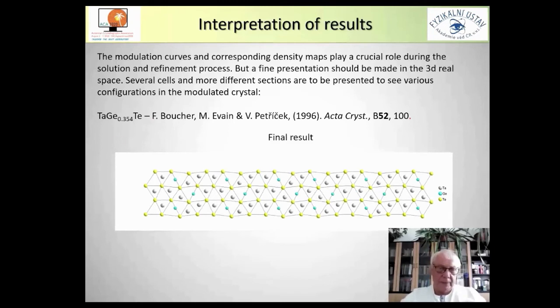If you are taking into account also positional modulation, you will see that these tellurium atoms are making more space if here it's germanium and less space if here it's a tantalum atom, which means that for the structure to be fully described, we have to use occupational and also positional modulation. This interpretation of the result gives the final answer of how the real structure looks like.